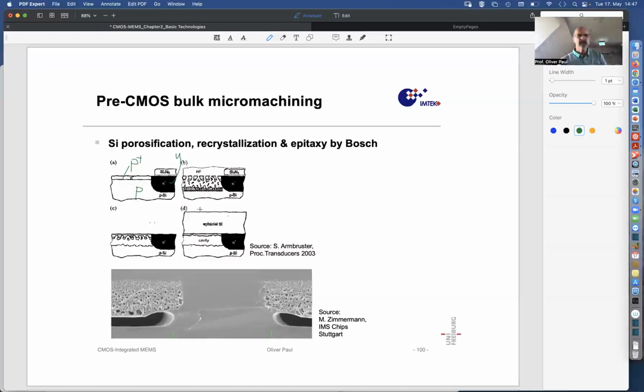And so there is this rough porous material buried below silicon, but at the high temperature at which you do that, the silicon in the cavity is so hot that the atoms on the surface migrate also, and they migrate to places where they are most favorably bonded. And so you can imagine this like a material with a surface tension that tries to make the area as small as possible to flatten it out. Water does not by itself become highly corrugated. It flattens itself to become flat. Of course, also under the action of gravity. It's also an effect. But the surface tension is an important effect, and so the surface tension makes this cavity hollow. Silicon is either migrating to the bottom or to the top, and then we have a cavity that is totally enclosed.